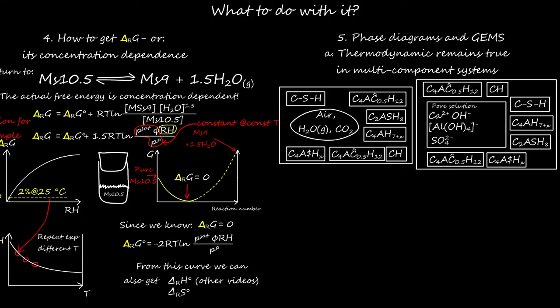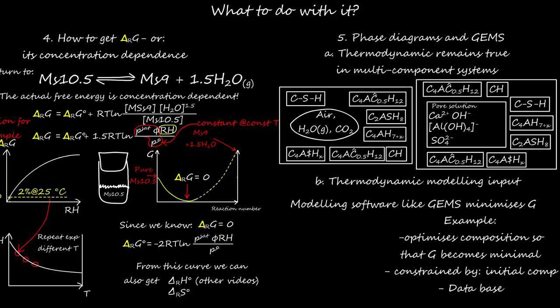Just think about our previous experiment with the sealed test tube, but imagine now there is some water-saturated ettringite present as well. Which phases will be present at the end and at which equilibrium relative humidity? We have learned that the total system will always try to minimize its free energy, so we need to figure out which phase composition has the lowest free energy. This is what thermodynamic modeling software like GEMS does. It minimizes the free energy of the system within the constraints of the initial chemical composition, which means, of course, mass is conserved. This is the motivation for work like Lewis' thesis. The thermodynamic software is only as good as its mostly experimental database, which needs to contain the thermodynamic information of all substances and the corresponding processes which they may undergo.